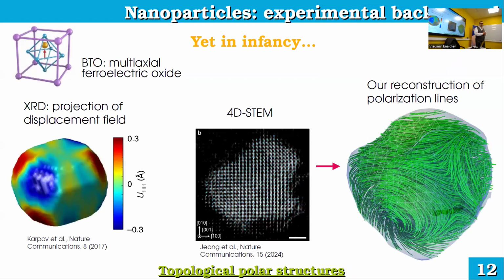Okay. Now we can talk about our results finally. So we start with nanoparticles. I already told that there is a lot of different research on very different geometries of ferroelectrics, but it's interesting that very few of them are about nanoparticles. Here are two prominent examples. One experiment on a pretty big barium titanate nanoparticle, where a vortex state was identified, and one very recent on smaller nanoparticles, about 10 nanometers in diameter, where also a vortex state was identified by the authors.